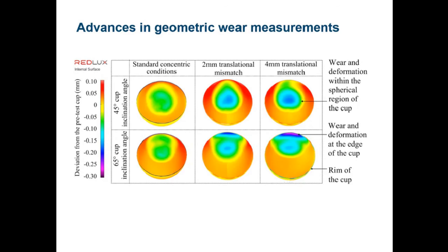Advances in geometric wear measurements were also made, and the image here is showing the pattern of the volume change on a polyethylene liner in a hip replacement, showing where the location of that wear and deformation is under different in vitro simulation conditions. The first column shows standard concentric conditions, the middle column shows a low level of mismatch between the femoral head and acetabular cup causing edge loading, but a 4 millimeter mismatch with a 65 degrees inclination angle causes a severe edge loading with a significant increase in wear and deformation at the rim of the acetabular cup.